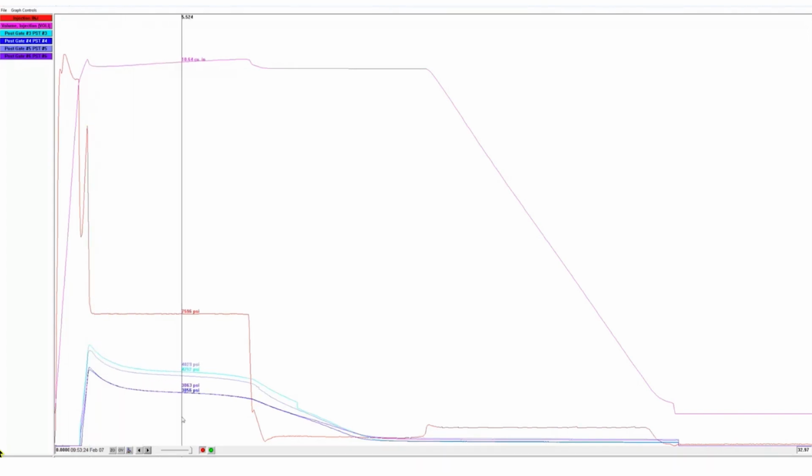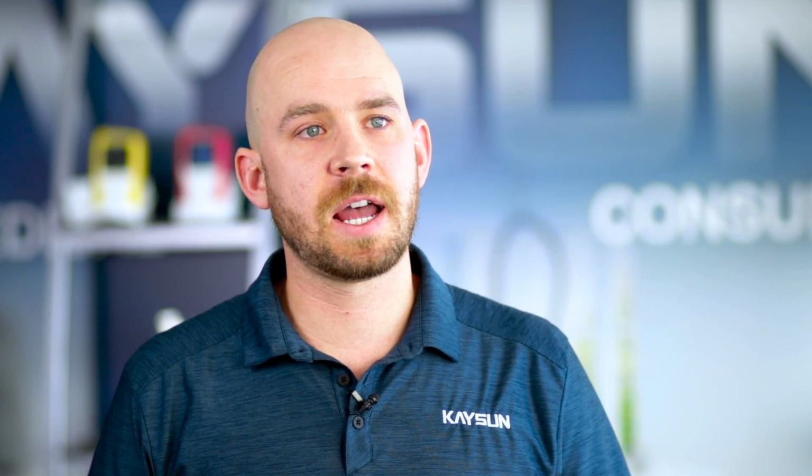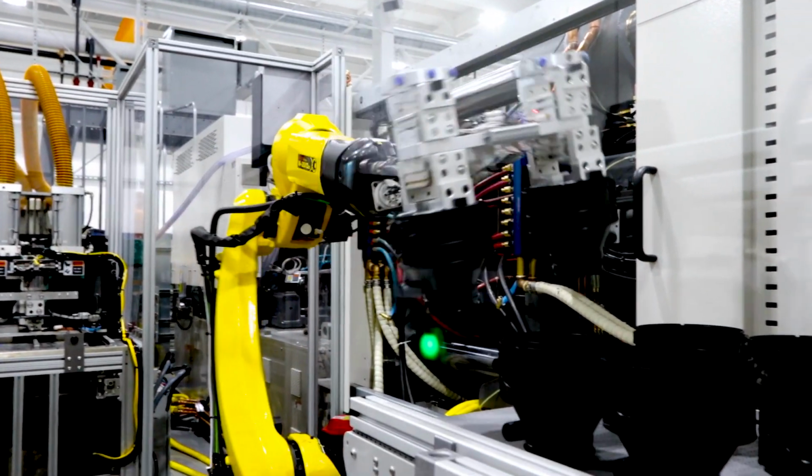One piece of technology that we use quite a bit while we're developing our processes is RJG. We install pressure or temperature sensors within each of our cavities in the injection mold, which allows us to monitor pressure within each cavity as well as melt progression. This allows us to monitor over time and make sure that we're matching those curves at the beginning of every production run to ensure that the process outputs are being met and matched from lot to lot of resin. Each lot of resin is going to process a little differently, and so we're actually monitoring the outputs that go along with each of those to ensure that we have a repeatable process from run to run.